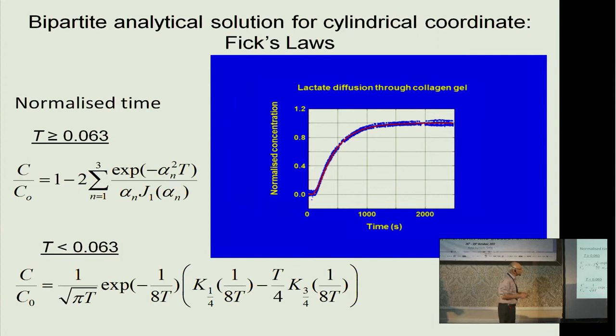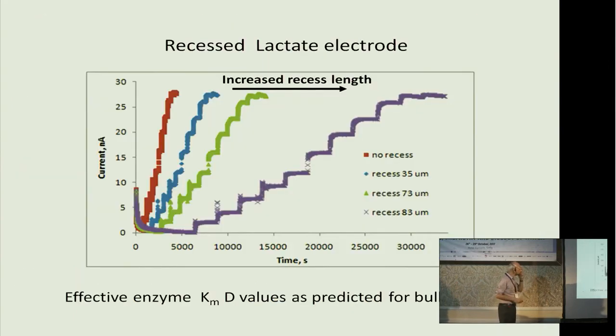So when you have identity of the two, you can pull out, somewhere out of this system, the diffusion coefficient. That's all I'm interested in. So, for example, if I have a sensing surface more and more recessed inside that recessed tip electrode, and I make the diffusion distances longer, then, for example, for the lactate enzyme sensor, which has an enzyme in it, I can extend the analytical range of that finite enzyme reaction and pull it out and out and out, simply because I made diffusion distances longer.